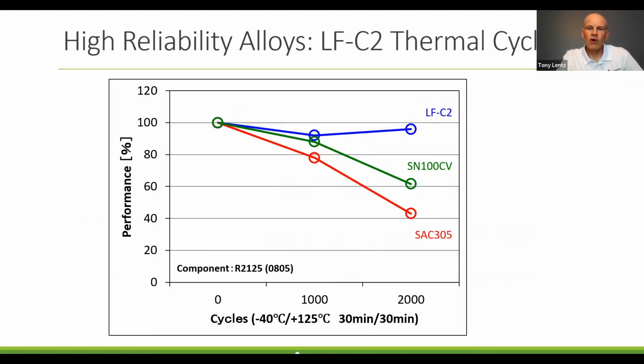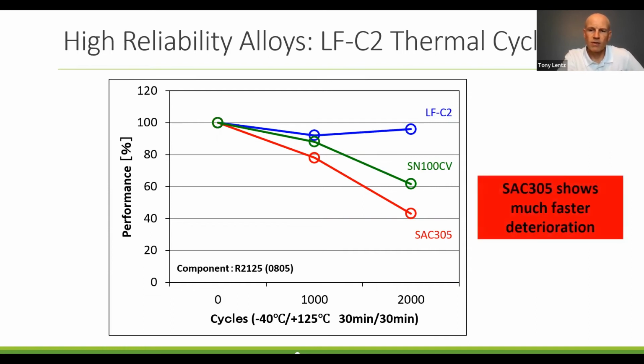Here's another alloy called LFC2, which is a high reliability alloy designed for the automotive industry. And this is a performance metric on the y-axis and then cycling on the x-axis out to 2000 cycles for a resistor. That's an 0805 size. So LFC2 is the blue bar at the top, and that maintained its performance even over 2000 cycles. SN100CV lost some performance over that period, and SAC305 lost even more performance. So it deteriorated much faster with thermal cycling.